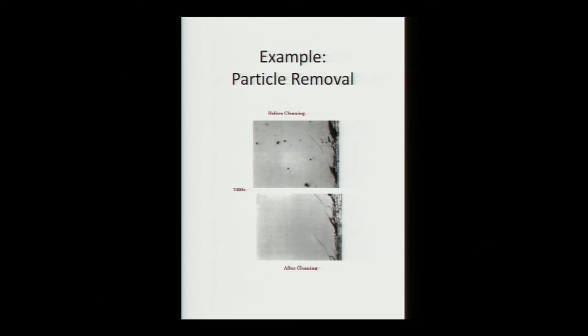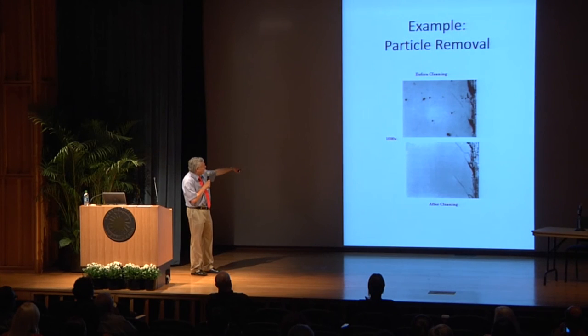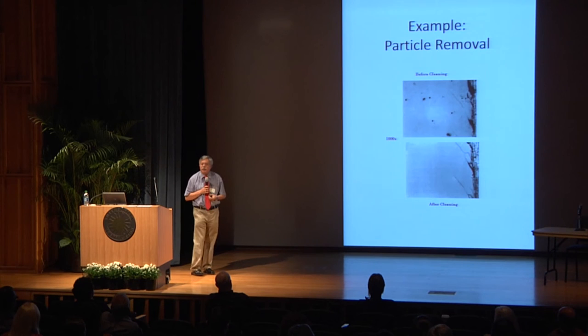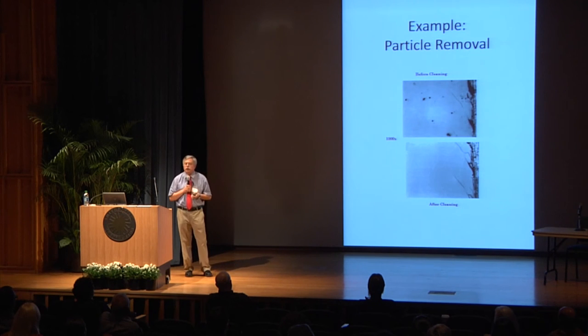This one is a silicon wafer that I scratched, and scratches on the right. And not only did we crack the surface, we also generated lots of particles. This is an optical micrograph at 1,000x, and after cleaning the exact same areas, there's nothing. This is a typical result you expect with CO2 snow cleaning.